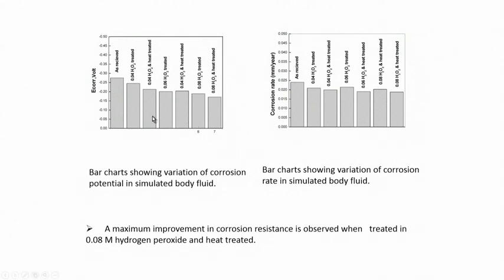So, we also carried out the corrosion resistance test in Hanks solution, because the objective of the coating was basically the application of this product as an implant. So, the solution was simulated body fluid, where we tried to see the leaching behavior of the oxide coated product. We found that as we go on increasing the oxide percentage, or maybe the hydrogen peroxide concentration in the solution, there was an increase in corrosion resistance in terms of ennoblement of the E corr value, and the corrosion rate was also decreased to a little extent,